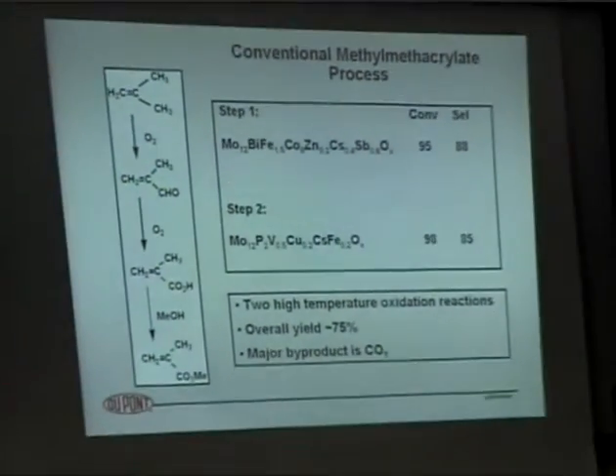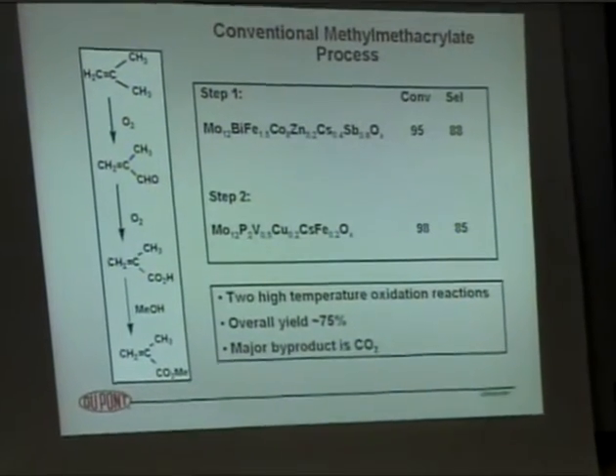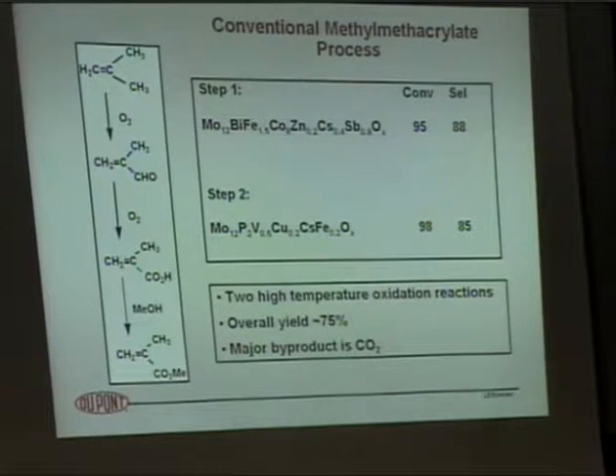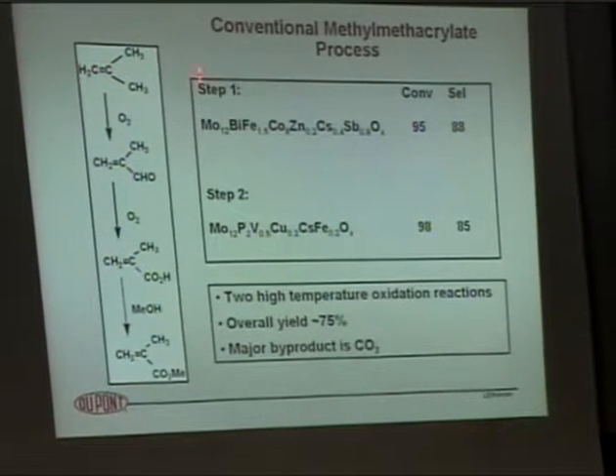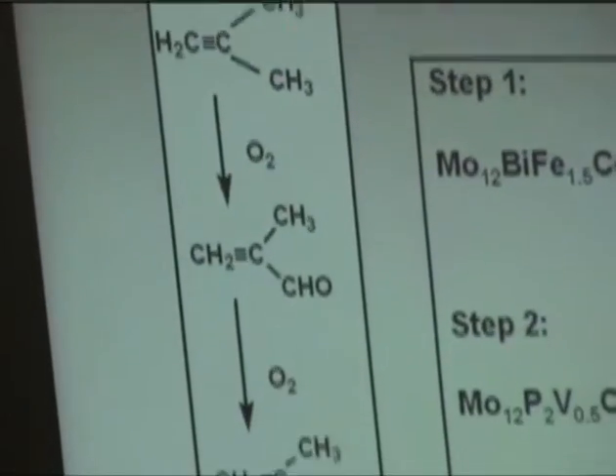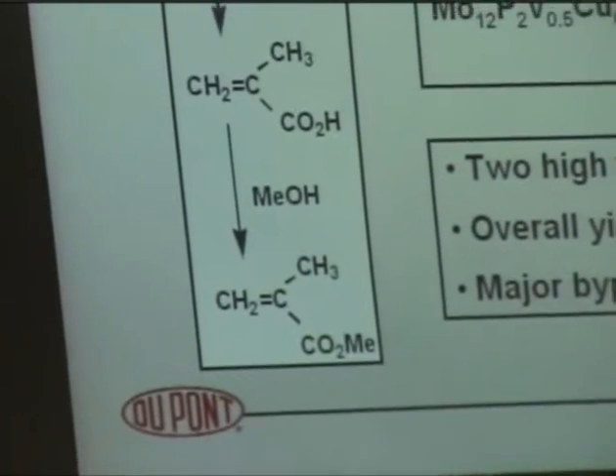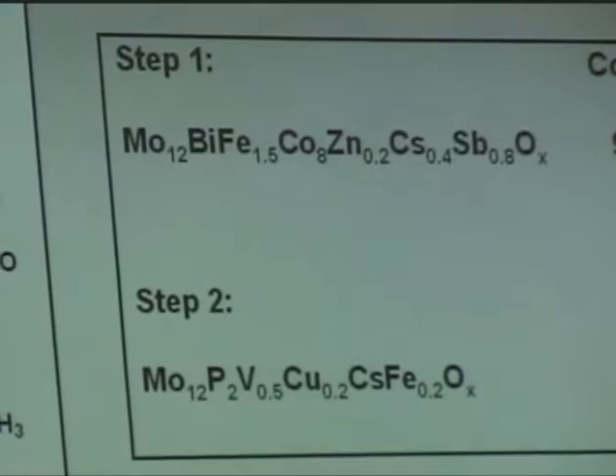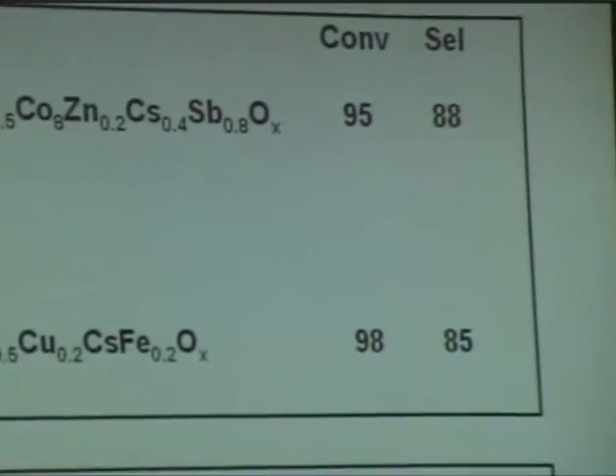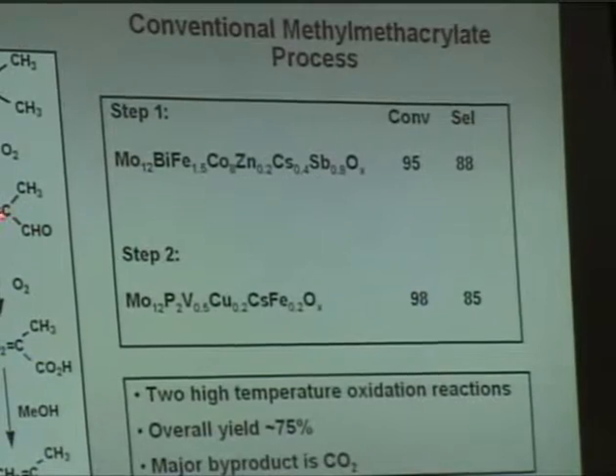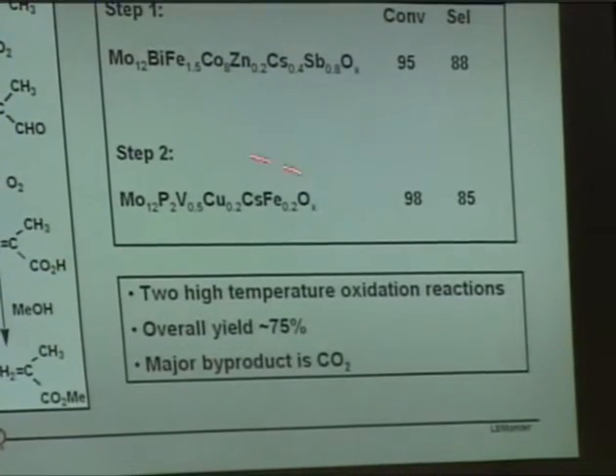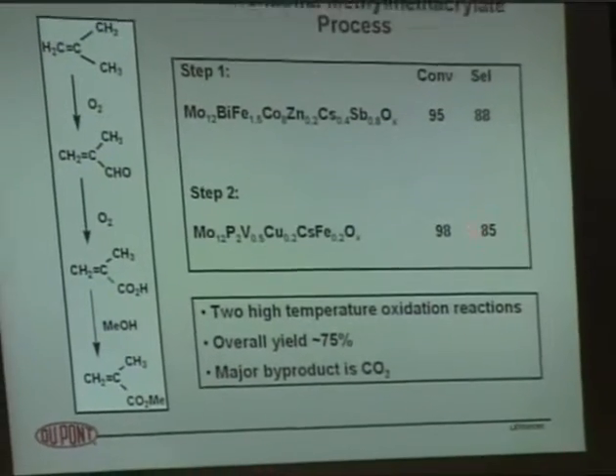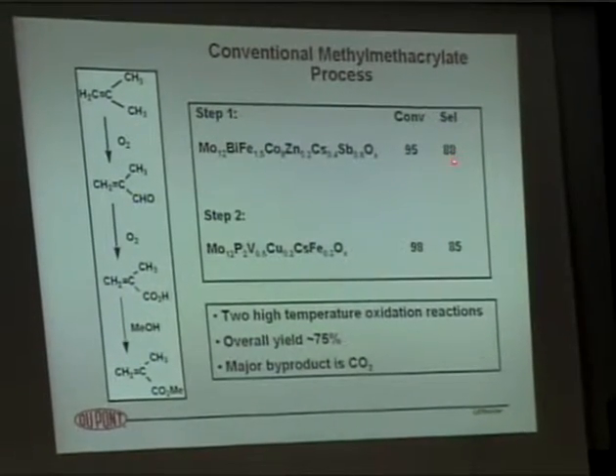Okay, let's go back now to the synthesis of methyl methacrylate. Goes into lucite and these Lexan shields and so on and so forth. Starting off with isobutylene, using a complicated metal oxide system. The oxygen oxidizes the isobutylene to methacrolein. Selectivity is not bad, high conversion to make methacrolein. Second step, traditionally or conventionally, is to oxidize the methacrolein to methacrylic acid. Complicated system again. Selectivity is not as high as it is up here. So the overall yield is around 75% to make methacrylic acid.